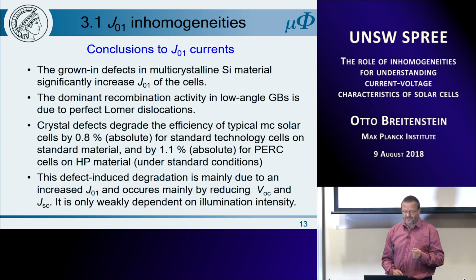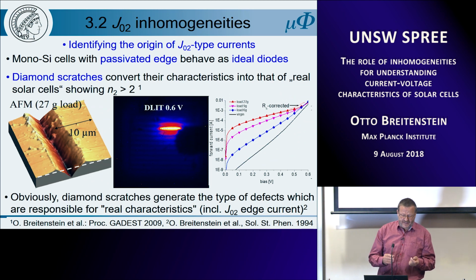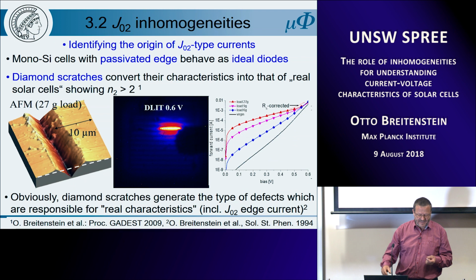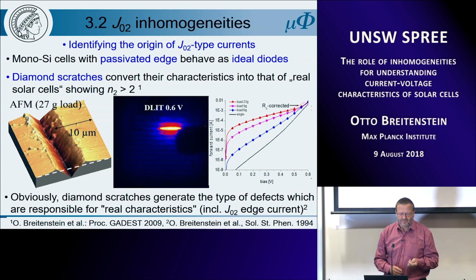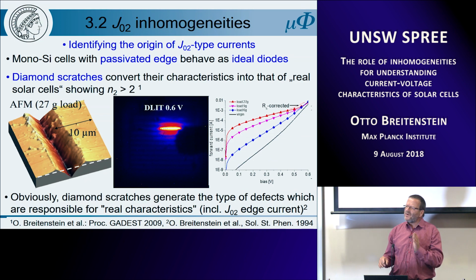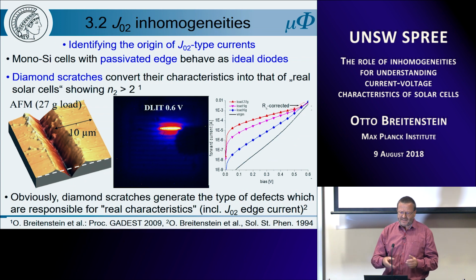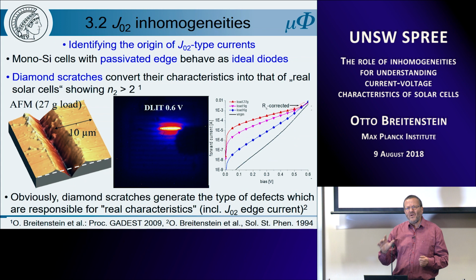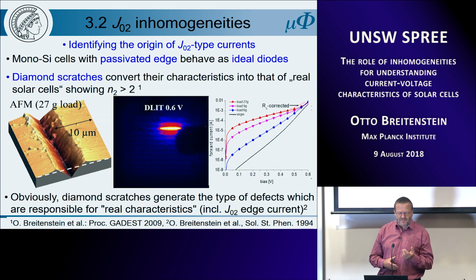Now let us come to J02. These are, by the way, results which date back from my working stay here some years ago. There I started with these investigations. We have found, and it was already known before, that if we have monocrystalline cells with planar technology, where the cell edge is passivated by an oxide, these cells behave as expected, as we have seen at the beginning, with an ideality factor of unity over a large voltage range. But if we scratch them, then we convert them into the characteristics as we measure it in usual industrial solar cells. So obviously, diamond scratches generate the types of defects which are responsible for the real characteristics.